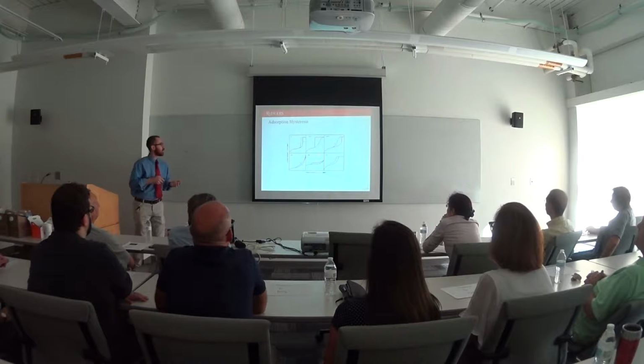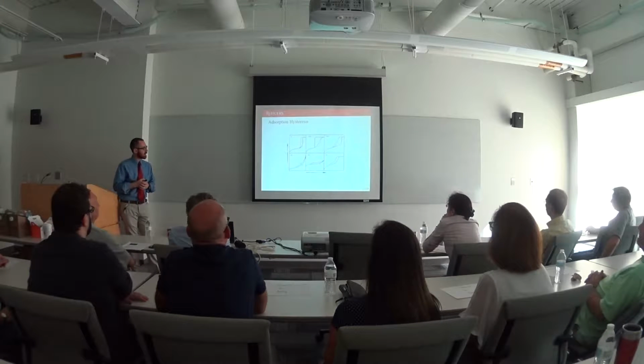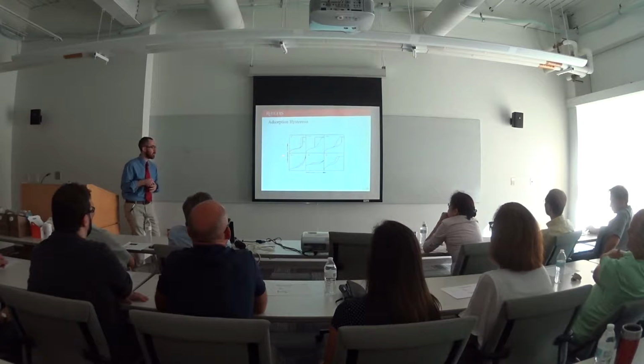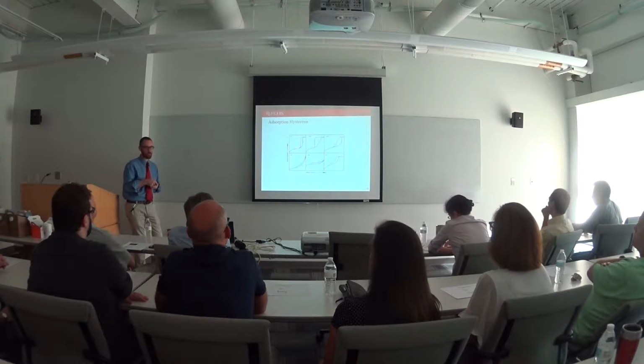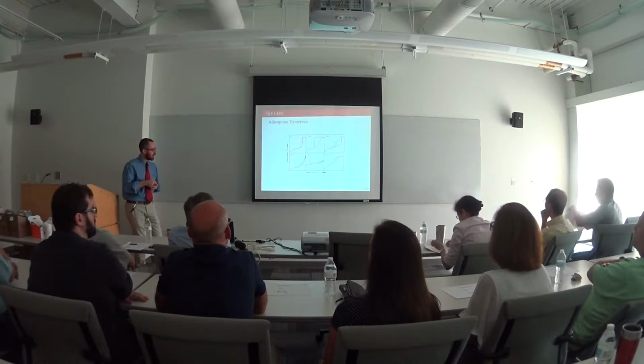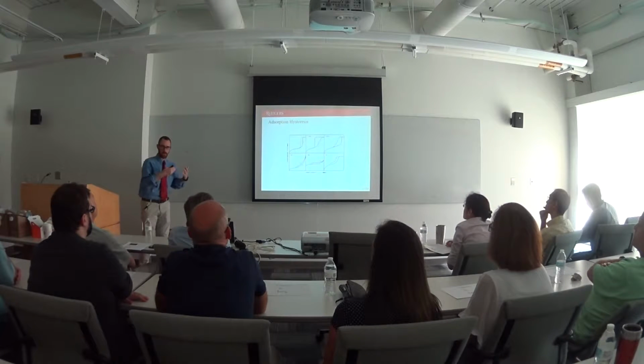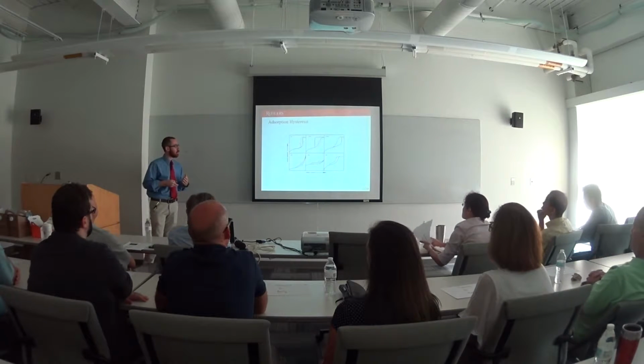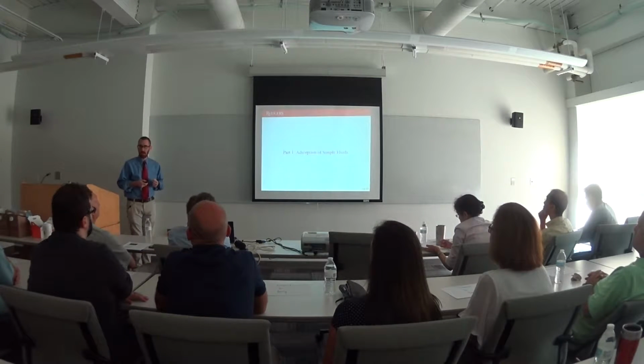Skipping those. So adsorption hysteresis is a special phenomenon which occurs in mesoporous materials. And I've done a lot of work specifically on characterizing hysteresis. Hysteresis occurs when the reverse process of adsorption, called desorption, doesn't follow the same path as the adsorption branch. Hysteresis curves vary greatly also based on the specifics of your material, and can tell us a lot about the pore structure. So, with that introduction, I can start talking about the first part of my research on simple fluids.